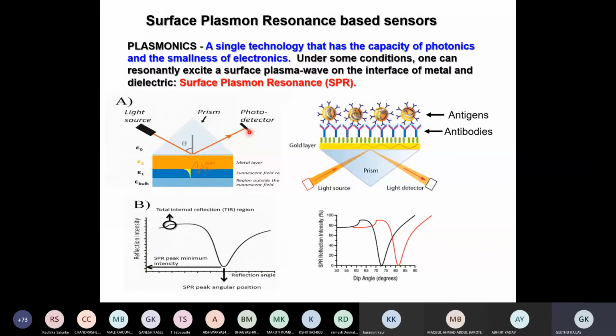surface plasmons, that is, surface plasma waves generated on appropriate conditions. You vary the angle so that momentum conservation happens, and then at certain conditions these plasma waves are generated at the dielectric metal interface. At that particular condition, you will see that the photodetector shows a minimum signal. In all other angles, you have a considerable amount of reflection happening, but when the SPR is generated, these plasma waves, the surface plasmon, the collective oscillation of electrons, are generated here. You have a dip in the signal. That is represented as a dip in this reflectivity versus angle curve.